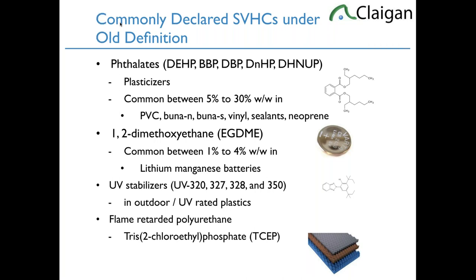But historically, the phthalates, orthophthalates, have been the plasticizers in PVC and nitrile rubber, Buna N and Buna S and neoprene forever. There are new replacements, especially the terephthalates. Terephthalates are not nearly as harmful. But when the orthophthalates are used, they're generally high concentration. They really don't do a lot unless they're high concentration. So normally they're 5 to 30% of the weight of the PVC. So a very, very high concentration.